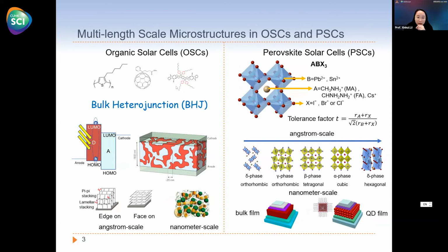So for organic solar cells, the organic donor and acceptor materials mix together to form this active layer, so that we can have abundant interface for the exciton dissociation. Here we are interested to see how these organic molecules pack in the semi-crystalline domain, which is the atomic scale microstructure, and how the crystallinity and orientation will affect the charge transport mobility. And how the donor and acceptor nanophase separate into different domains, which will affect the exciton dissociation and charge collection process. This belongs to the nanometer scale structure.